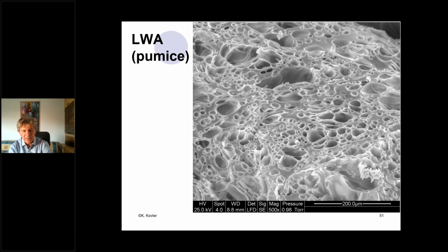And this aggregate can disintegrate during mixing, and then as a result, we have a dramatic increase of slump. So we can see the workability, the plasticity, flowability is changing dramatically. It is a direct result of premature liberation of water. So this is not good for us. We need to lock this water for a few hours, not to be considered as a part of mixing water.